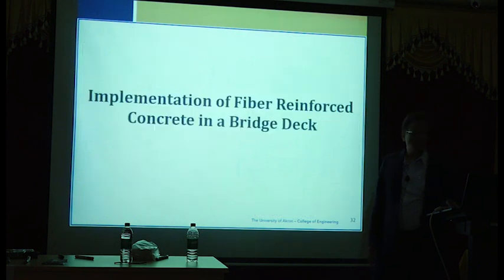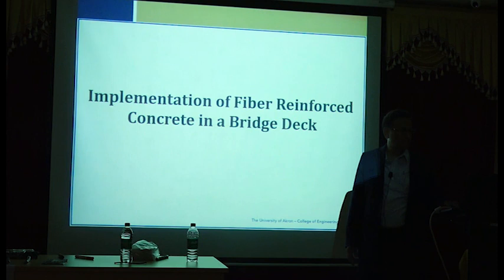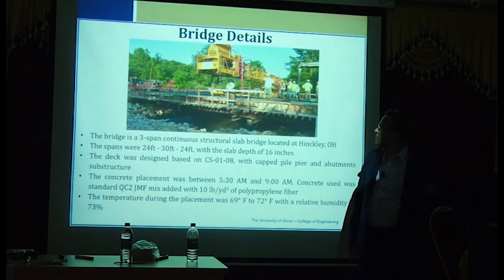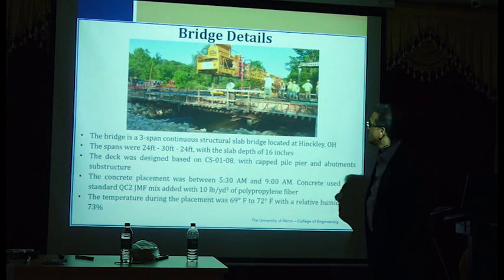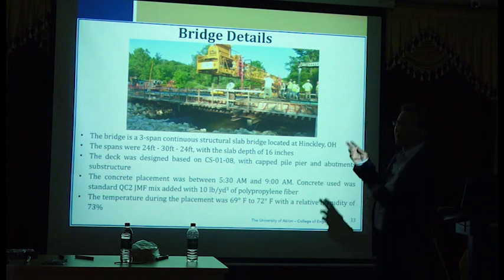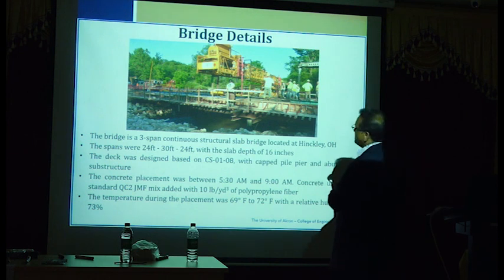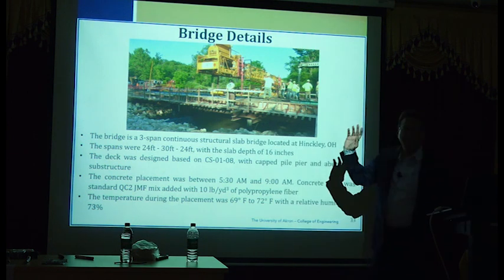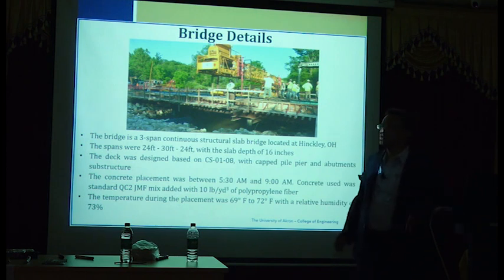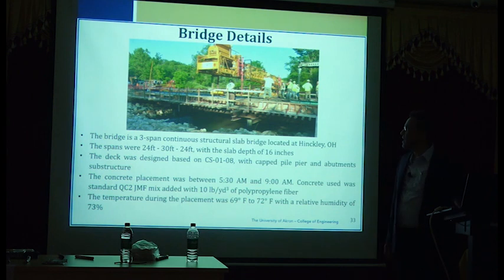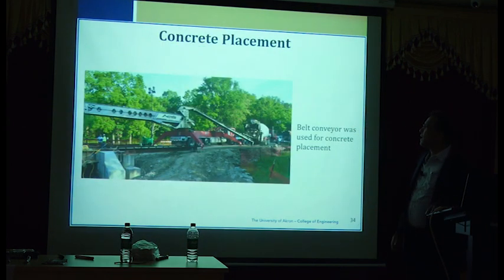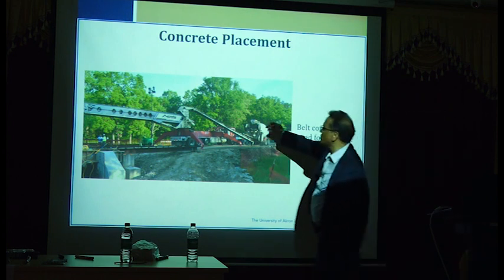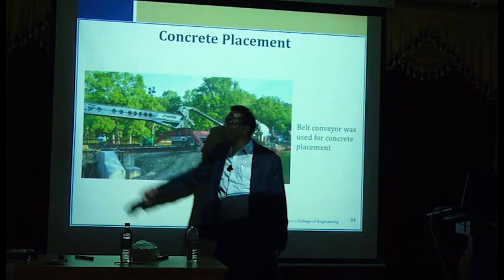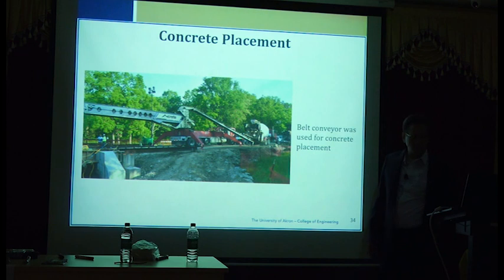When the sponsor, the one who gave us funding, looked at all the results, they were very happy. They said, let's implement this in a bridge. So that's a bridge we used in one of our nearby counties. We did a 3-span bridge with polypropylene fiber at a dosage of 10 pounds per cubic yard. We were not able to use the pump, so we used a conveyor. You dump the concrete here, it is conveyed on the conveyor belt, and it worked very, very well. Very good surface. Everyone was very happy.